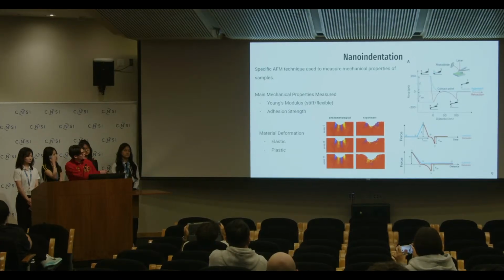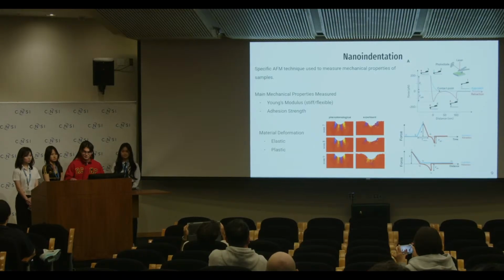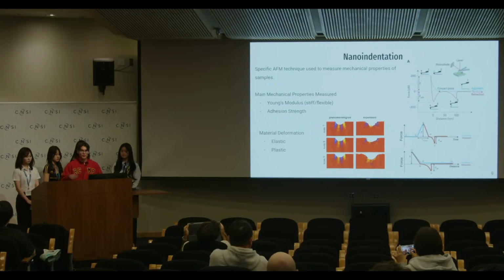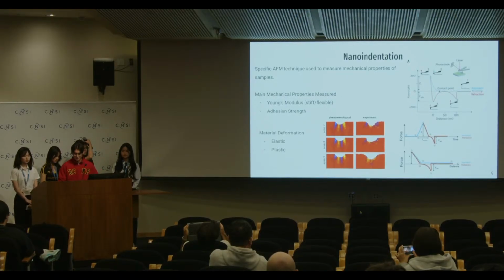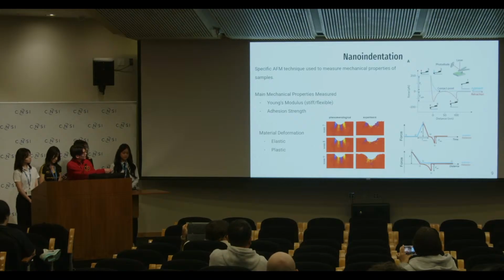This data is used to create force distance curves, which is this one. The blue line is when the probe approaches the sample, and the red is when you're moving the probe away from the sample. These force distance curves tell us about the Young's modulus, which, as you know, is the stiffness, and if the material deformation is elastic, which is temporary, or plastic, permanent. As you can see on this image, this material deformation is plastic, how it's keeping its deformed shape.